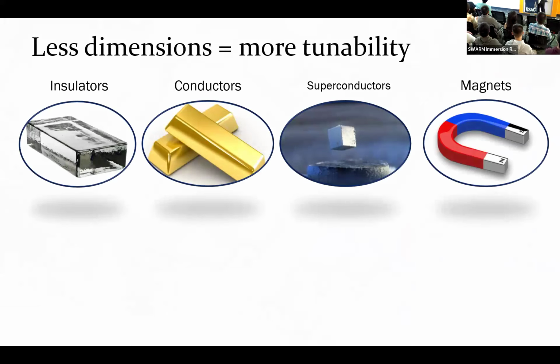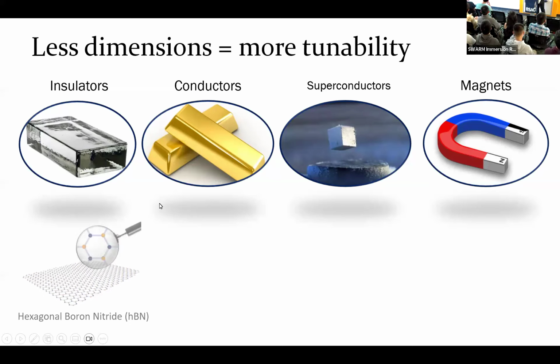So in one sentence, why we want this lower dimension is because lower dimensions give us more tunability. And I'll give you an example to show you what that means by more tunability. Nature gave us a lot of these materials that can be classified by, for example, their electrical properties, whether they're insulators or conductors, or superconductors, which conduct without any resistivity, or magnetic properties as well. And it turns out that you can thin down these materials to their monolayer limits, which means material with 1 atom thick. And those materials still retain these properties of the bulky forms.